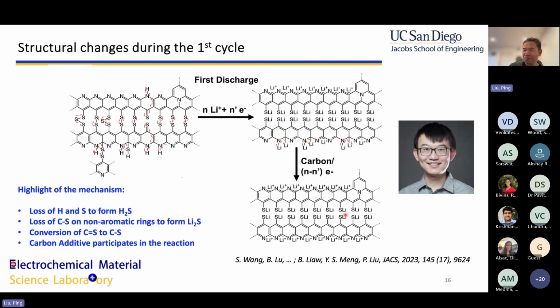Where does the lithium go? And what functional groups does the lithium react with? And in fact, during the first cycle, we even observed some irreversible transformation, including the formation of H2S during discharge, which is not great, after which the material becomes more conducting. Now, how do we put in more sulfur? It turned out the secret of this structure is that it can bind with very short chain sulfur, like 2, 3, not quite 4 sulfur chains.